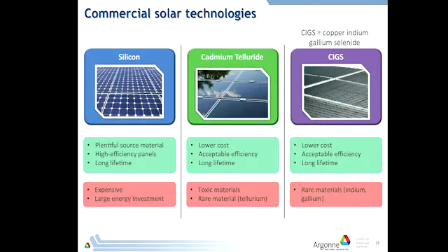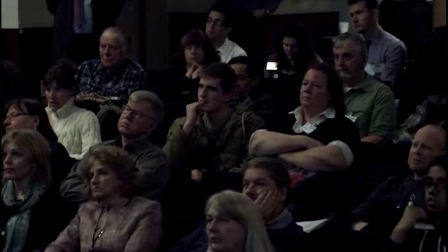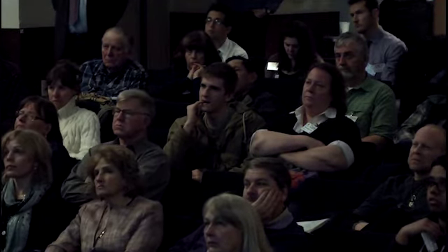And if we look at what's available currently, commercial solar cells, there are lots out there and more people are using them. They're based on silicon or on cadmium telluride or on CIGS, which is copper, indium, gallium selenide. But silicon is expensive to process, and so you have a large investment. Cadmium and tellurium and some of the elements in CIGS are rare, and that's a problem if you're going to run out of the materials. Also, cadmium's actually quite toxic, which again is not ideal. It's still within cadmium telluride, so when it's actually in the solar cell, it's not a problem, but the problem comes at the end of the life of the solar cell when you have to generate the waste materials. And so none of those really fully address what we need for solar energy.